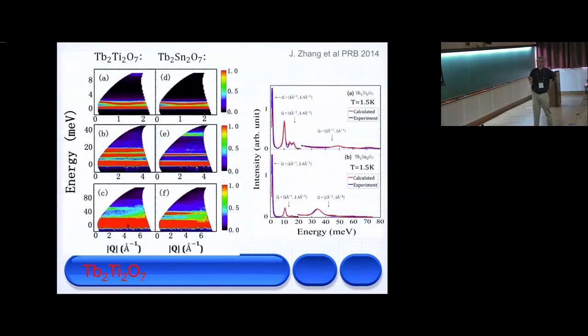This is really why I put terbium titanate in. Tomorrow you'll have a talk on the crystal fields of some of the pyrochlores. And with neutron scattering, there are these huge instruments now that come in with high energy neutrons. In this case, it must have come in with something like 100 meV, and then it looks at all the scattering from 100 down, and you get these bands. The resolution of the machine depends on that incident energy, so to get a full understanding, you have to do something like this, where it's at 10 meV and down. This must be about 50 and down.